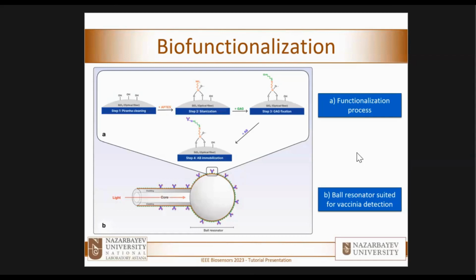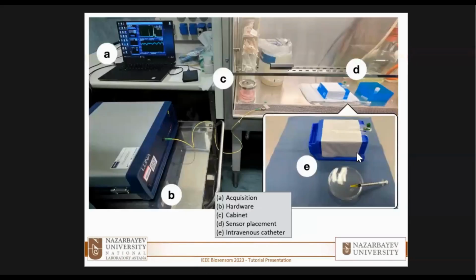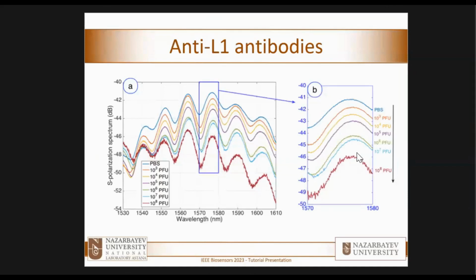The functionalization that we have made is exactly the same, and we have tested 2 antibodies. One that is the L1 protein, the best performing one, and one that we synthesized from rabbits. So rabbits were inoculated the virus, and we got the antibodies, synthesized and purified those antibodies, and we could compare the 2 results. That's our setup. So again, the hardware, that's not our lab. That's because we made these measurements in one of our partners in Milano, in Italy, where we actually have a lab with the appropriate biosafety level, and where basically we could place right here our ball resonator. And we have investigated several of them.